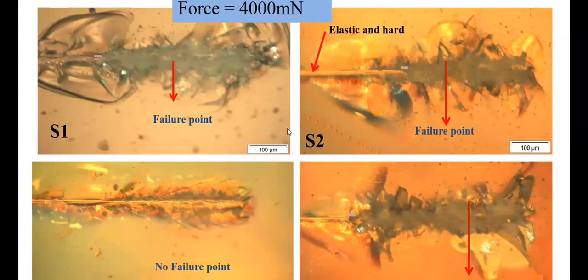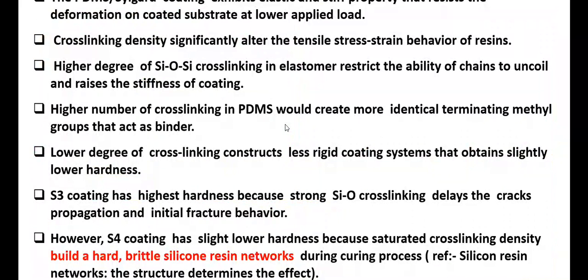Okay. So from here, we can conclude that the PDMS-Sylgard coating exhibits elastic and stiff properties that resist the deformation of the coated substrate at lower applied load. The cross-linking density significantly alters the tensile stress-strain behavior of the resins. A higher degree of silicon-oxygen-silicon cross-linking in elastomers restricts the ability of chains to uncoil and raises the stiffness of the coating. Okay.